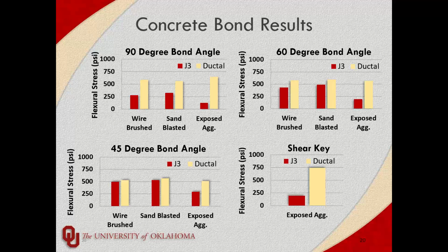Well, we lowered our silica fume to improve our workability, but I think there's potential that the silica fume may increase that bond strength because it is such a fine particle. It's so small, it's more likely to get into the crevices and the pores of conventional concrete. So I think it improves the bond strength.